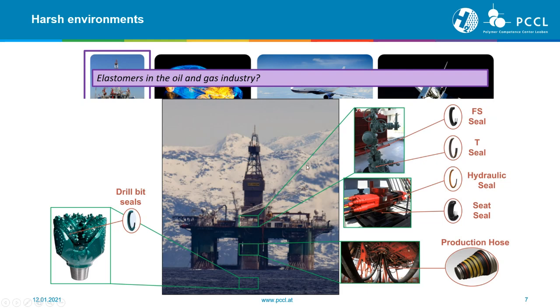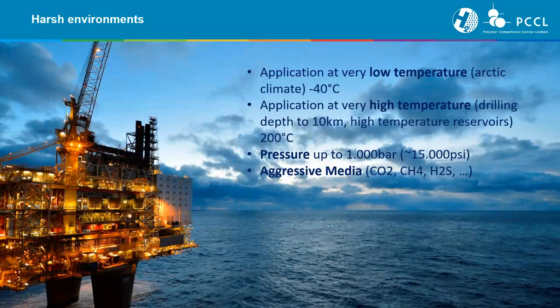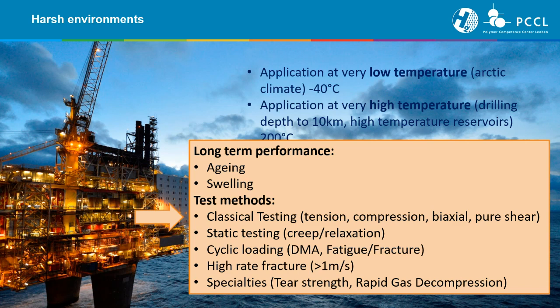More or less here we have these different applications, and what they have in common is that we have a variety of influencing factors on the material. So when we are thinking of applications at very low temperature, for example Arctic climate, we have temperatures down to -40. When we think of very high temperatures, drilling depths up to 10 kilometers, for example, or high temperature reservoirs, then we have temperatures up to 200 degrees. Pressures up to 1000 bar in combination with very aggressive media. And all of this leads to an impact on the material performance, on the long-term performance. So for our material and application we will receive aging, we will receive swelling when we apply oil, gases.